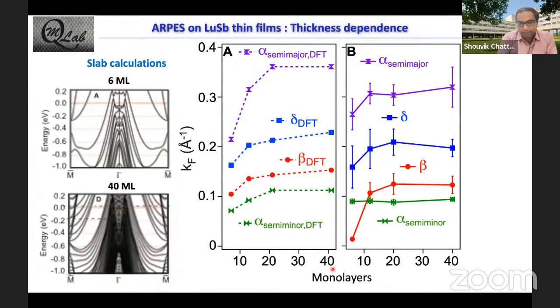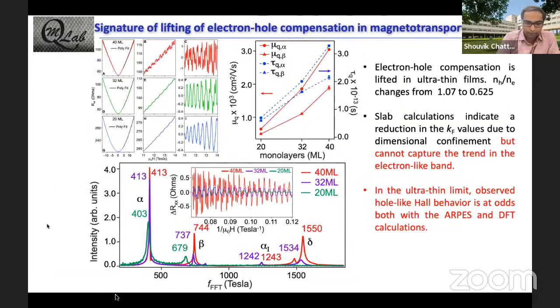That is one. The second part is that we can also try to do the same thing by looking at the quantum oscillations, and we do get quantum oscillations till 20 monolayer. And you can see here that the frequency corresponding to the electron-like pocket suffers very little change, but there is a very strong change in the hole-like pockets. So this again corroborates what we see in the ARPES, that as you go thinner, we can lift the electron-hole compensation, where we have a much higher carrier concentration for the electron-like carriers as opposed to hole-like carriers. But now there are two issues here.